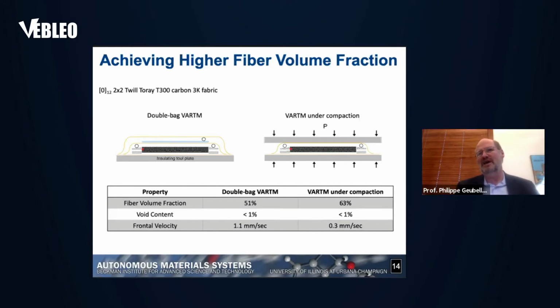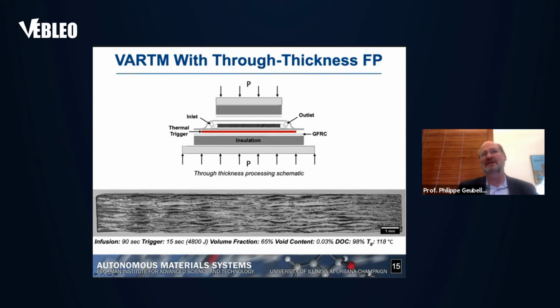But obviously, the more fibers we have, the less resin, and all the heat is associated with the exothermic reaction in the resin. So another approach, instead of going from, let's say, left to right, from one end to the other of the specimen, we can actually achieve this frontal polymerization from the bottom up by using the thermal trigger at the bottom of the specimen. And here's a part that we made fairly recently where the volume fraction is 65%, and the trigger is just run for about 15 seconds. Now, there's the infusion process, which took about 90 seconds. So the point is we can achieve very high quality composites much faster than the traditional way using this approach.